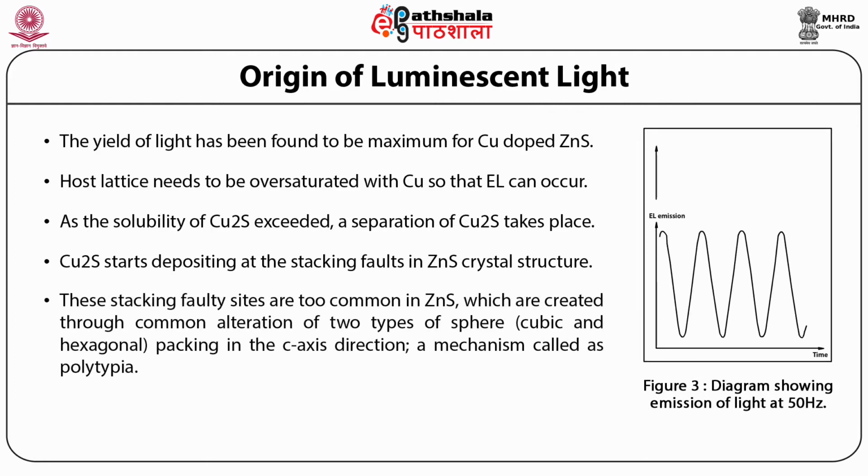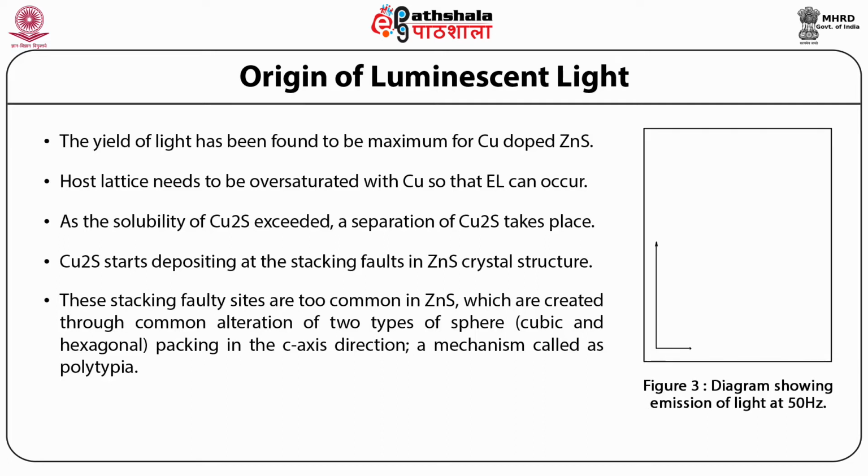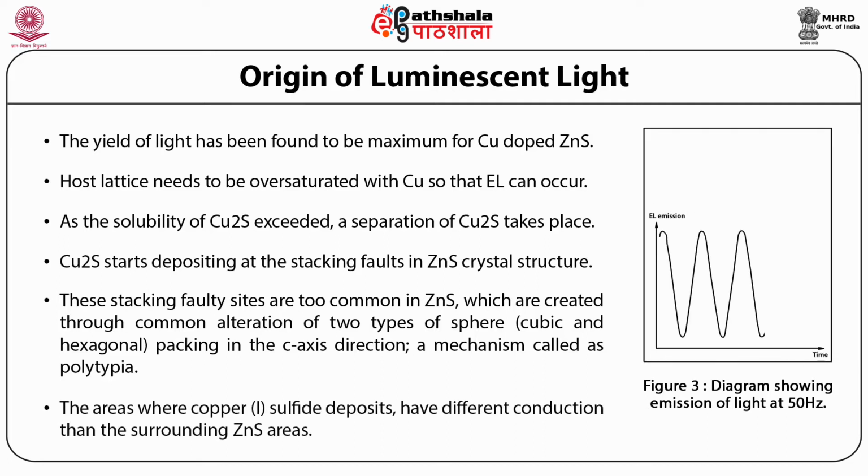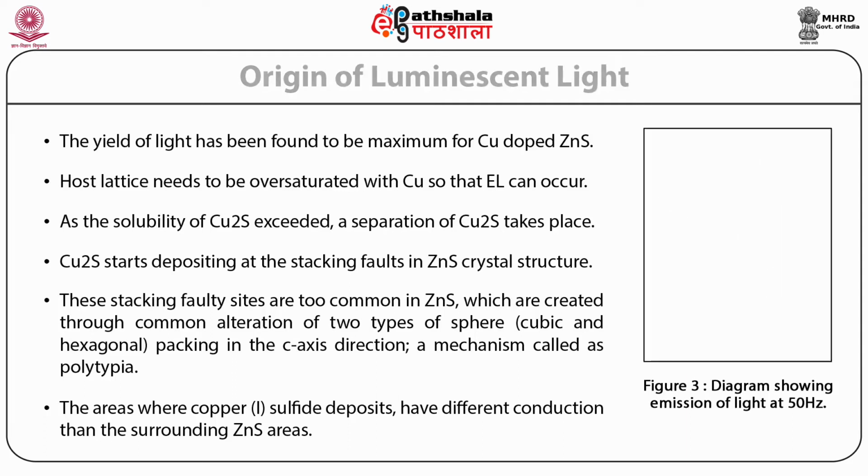These stacking fault sites are very common in zinc sulfide. They are created through common alteration of two types of sphere packing, cubic and hexagonal, in the c-axis direction, a mechanism called polytypia. The areas where copper 1 sulfide deposits have different conduction than the surrounding zinc sulfide areas.